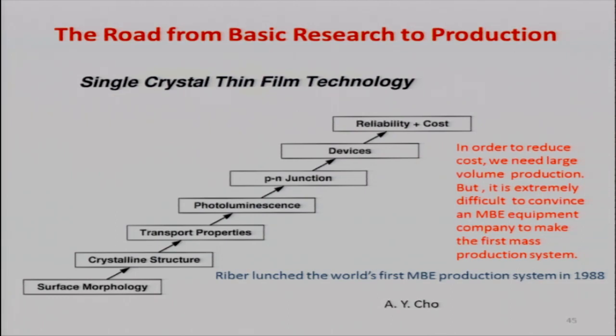The road from basic research to production is a long road. I just want you to have some feeling for it. For crystal growers like us, we first grow a layer, we look at the surface morphology, take a picture with a Nomarski camera, and then we publish a paper. The next difficulty is the crystallinity of the structure. Are you polycrystalline? Are you a single crystal? Is there a defect in there? The next level up is transport properties. If you grow a crystal, you measure mobilities. The mobility can be terrible because of traps and all the other things in there. You have to grow very high purity material to get high mobility devices.